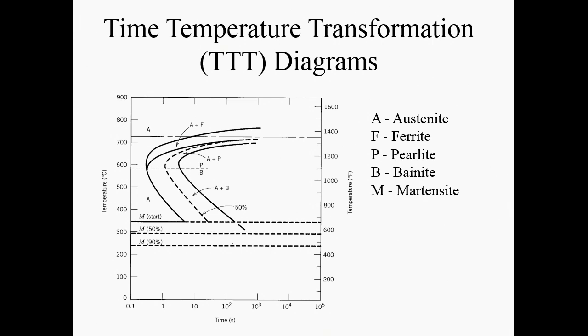If we cool so quickly that we got down to here, so we managed to miss all these thermodynamic transformations, with steels you can get another material formed, a material called martensite. It was named after Professor Martens. He put the "ite" on the end of his name. And this is a very hard and very brittle phase of quenched steel. It's used for cutting tools, it's used in gears and bearings and things where we want very high strength. It is what often causes the failure in welds, because the martensite forms due to high cooling rates, because we've missed the thermodynamically stable transformations, we've cooled too quickly. And we want to try and avoid that.